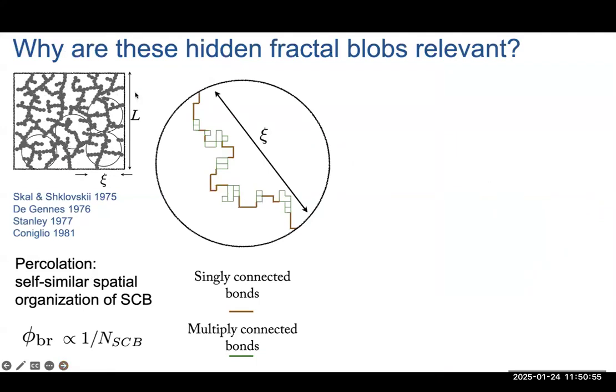And so why is that important? Well, when you have something like a gel and a structure that is becoming rigid through a percolation process, people have studied this type of phenomenon a lot, and thought that this percolating cluster that you form can in fact be recapitulated in this type of blobs, links and nodes model, where you have blobs whose size in fact increases as you approach the percolation threshold.